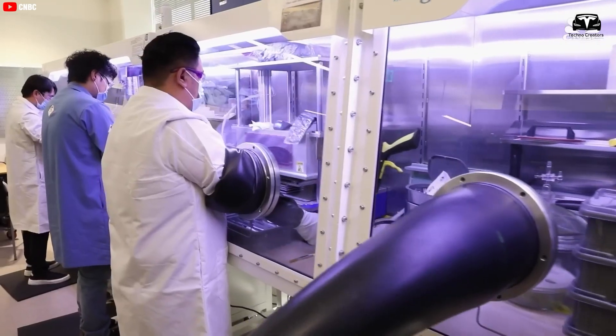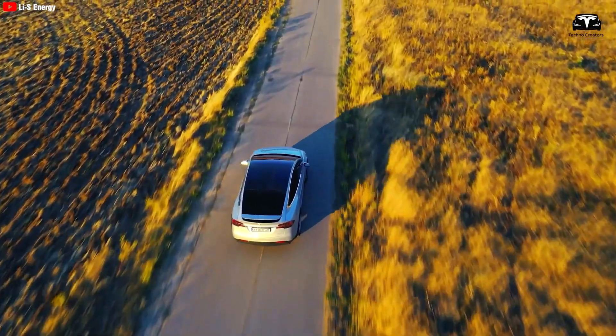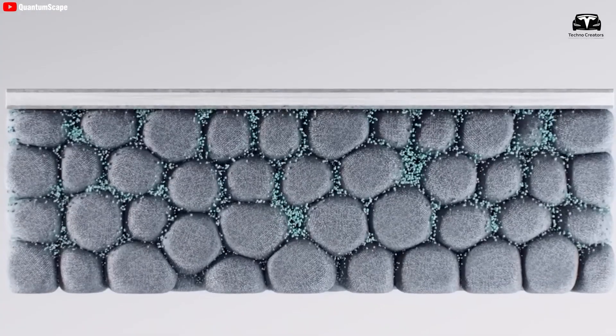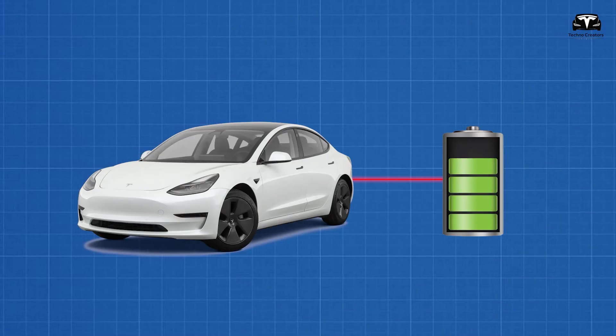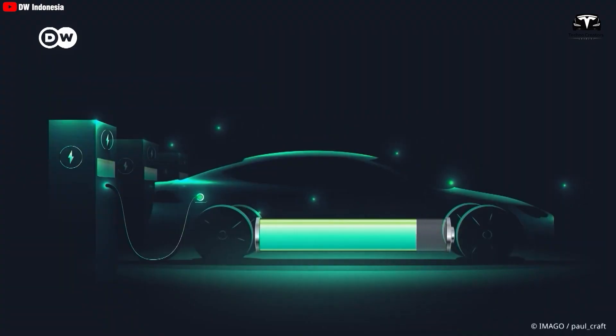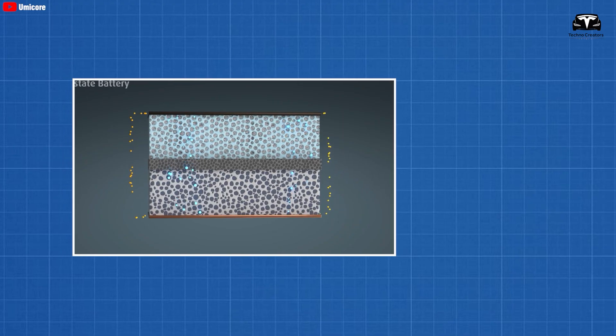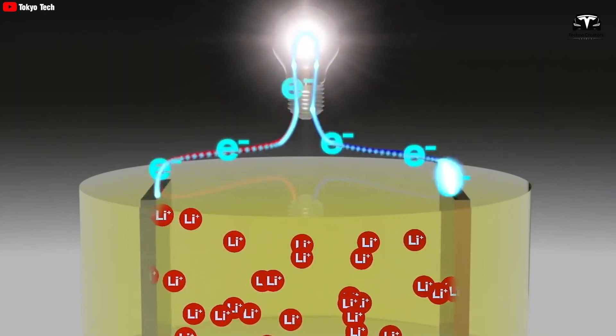The materials used in today's EV batteries, such as graphite in the anode, have physical limitations that can cause permanent damage when charged rapidly, reducing the vehicle's range. This often forces EV drivers to choose between the convenience of fast charging and preserving their battery range. Solid-state batteries use solid electrolytes with high ionic conductivity, which accelerates the lithium-ion transport process and speeds up charging — achieving up to 80% charge in 15 minutes with less detrimental effect on lifespan. There are two common types of electrolytes in solid-state batteries: sulfide and oxide. Sulfide electrolytes are noted for their excellent ionic conductivity, enhancing charging speed because ions can move through sulfide more easily, leading to faster charging times.